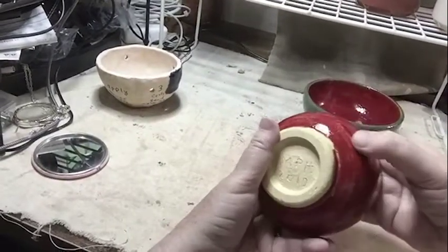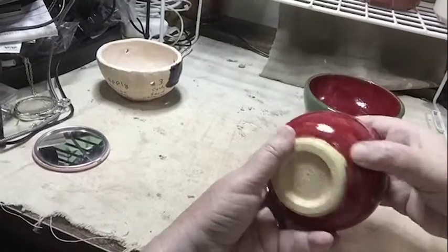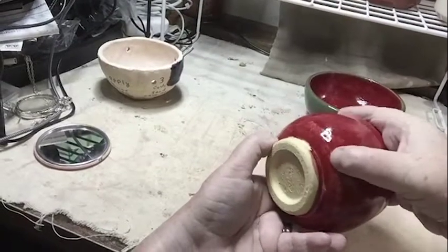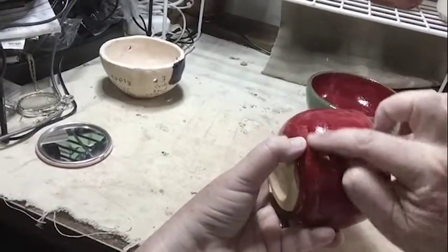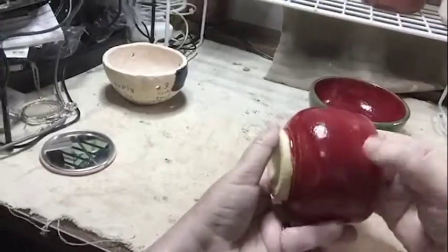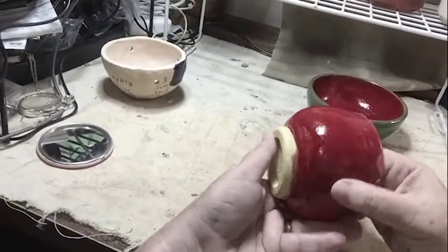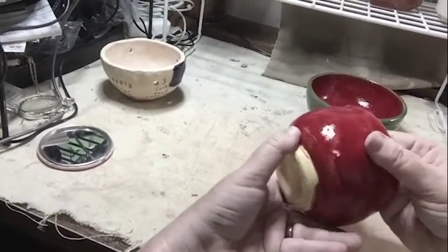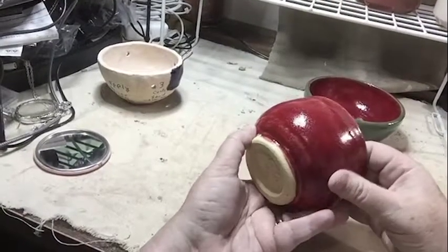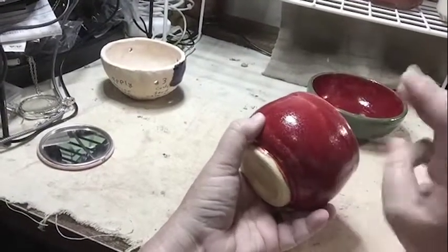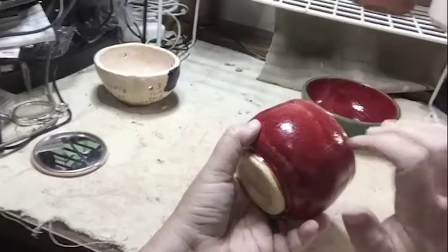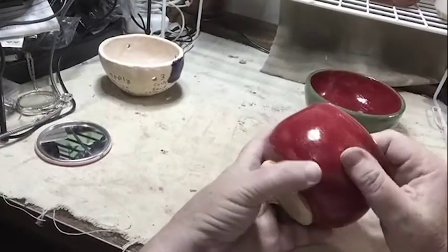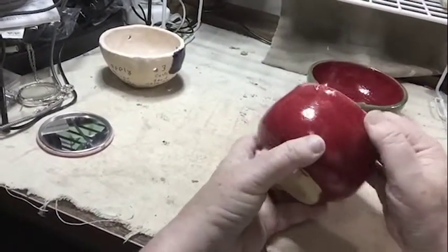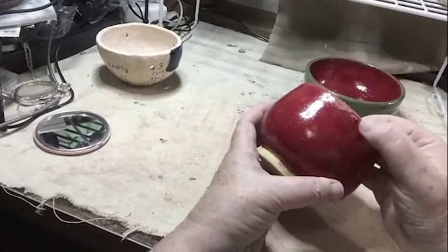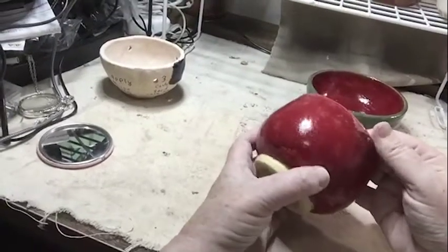So it got really bad down here. You can see where it's super thin, it's super thick here. This is a good example of a bad application of glaze. So when you are glazing something with a brush, you want to make sure you do 3 even coats, and you want to let each coat dry in between before applying the second coat. Let that dry, then apply the third coat.